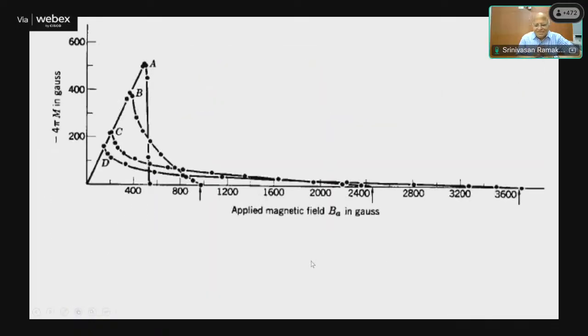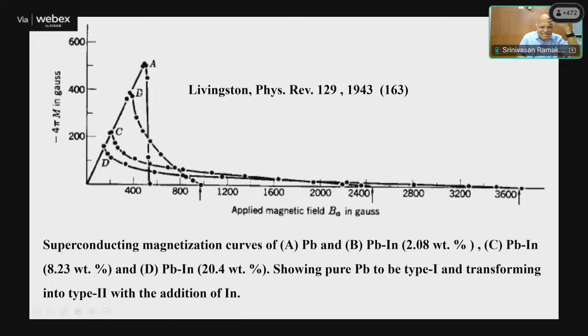So this is the typical experimental value of the critical field in lead. Depending on the applied field and different samples, you start with lead, then you add indium. Lead is a type 1 superconductor, so you will see only one curve like this, the thermodynamic critical field, type 1. When you add indium, slowly it becomes a type 2 superconductor. For instance, the last curve, where you have the maximum indium, 20.4, is a type 2 superconductor.